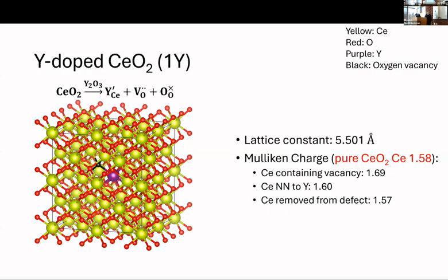And I did do a brute force calculation to see how the dopant and vacancy would like to reside. And the most favorable formation energy was for them to be bound to each other.